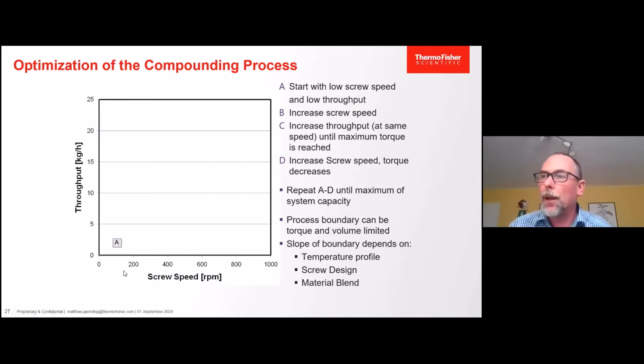So as a recommendation, we would not start at minimum speed, something below 10 or so. That doesn't actually make sense because the screws are turning very slowly, and the residence time is very high. So let's start at something like 50-100 RPM. We start at point A, low screw speed, but not lowest, and a low throughput.